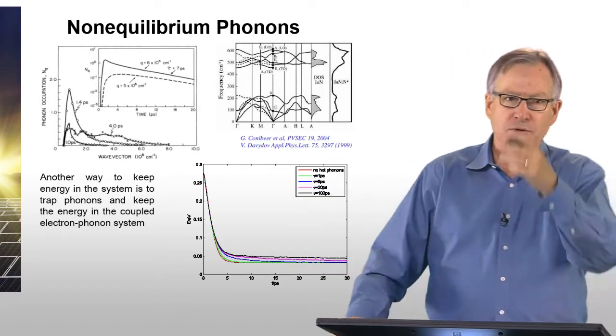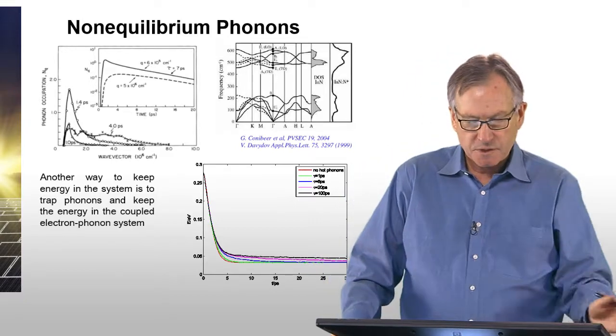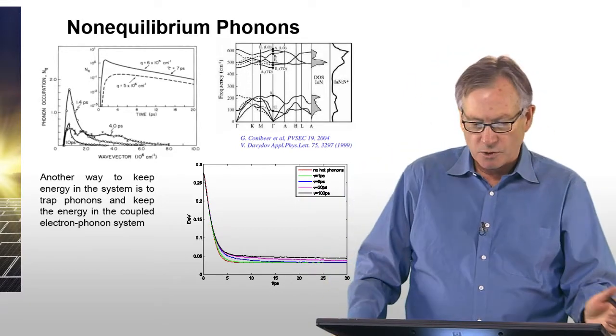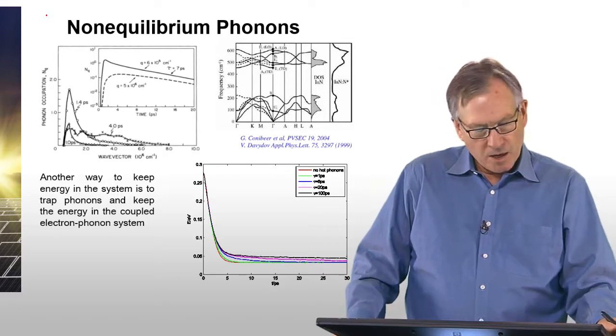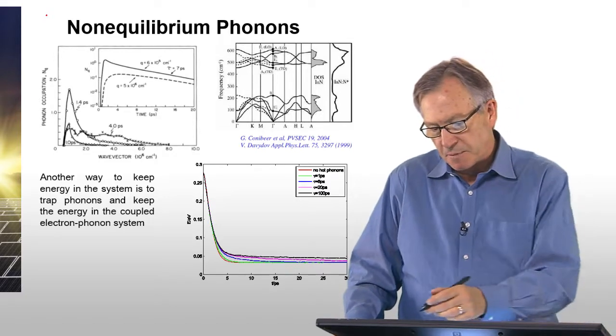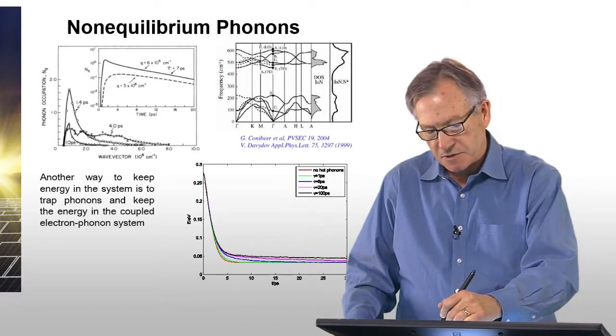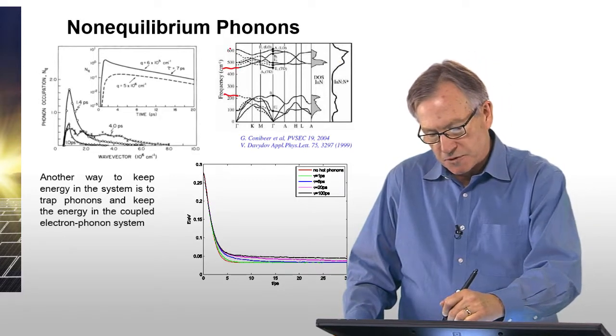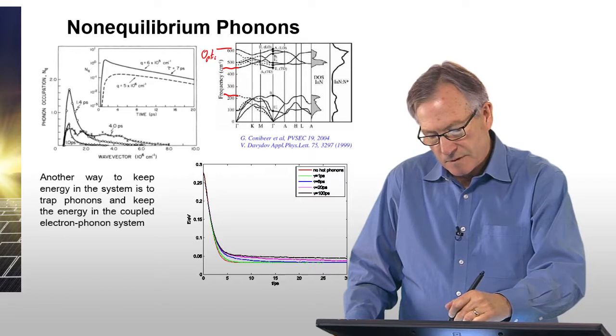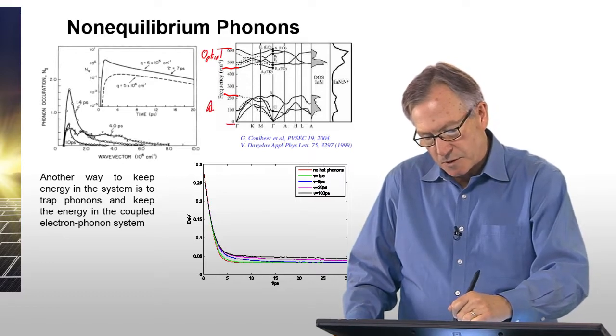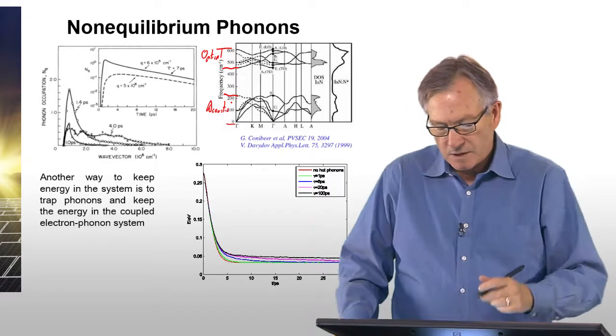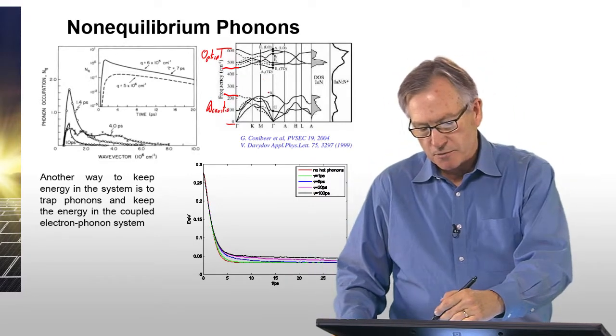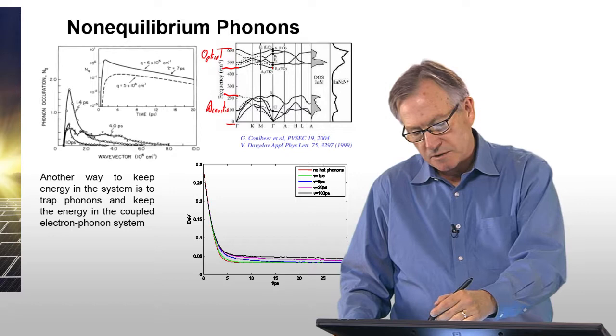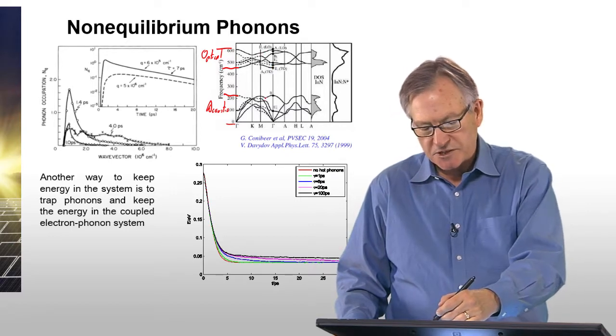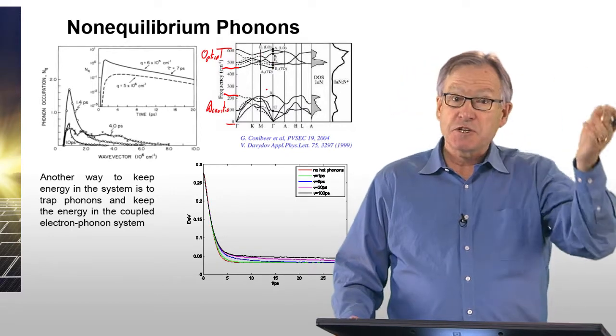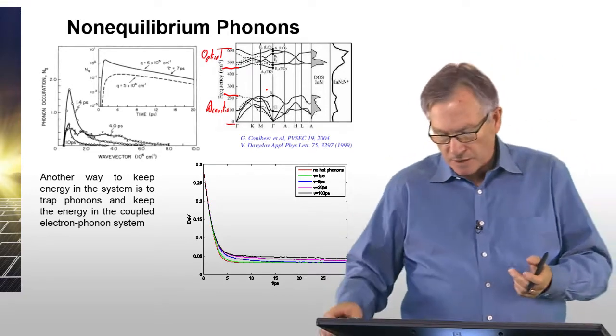So if you can prevent the optical phonons from decaying into acoustic phonons, you can keep the energy in the system, and this is the so-called non-equilibrium phonon approach. And there are certain materials, indium nitride, for example, in which the separation between the optical modes, which are these modes, and the acoustic modes, which are these modes, is separated by more than an optical phonon energy. So therefore, there's no direct channel for an optical phonon to relax and become an acoustic mode. So that means that you can get relatively long lifetimes, theoretically.